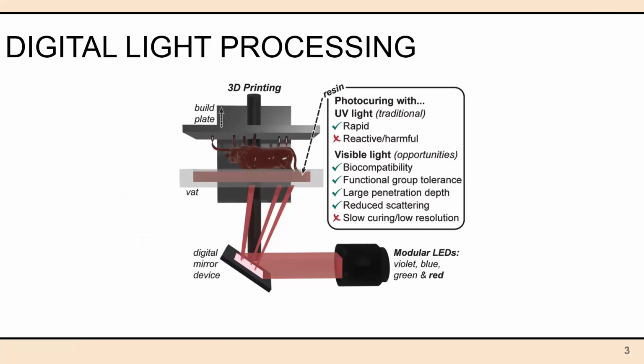However, the issue is that a lot of DLP methods today utilize UV light to do their printing. While UV light is pretty rapid to cure, it's also rather energetic, and that can degrade the quality of your prints, along with the fact that it also prevents biological applications. Visible light, however, gets you a lot of these advantages, such as biocompatibility, functional group tolerance, larger penetration depth and reduced scattering, but it's also rather slow to cure, and the resolution of the prints generated is also rather low.